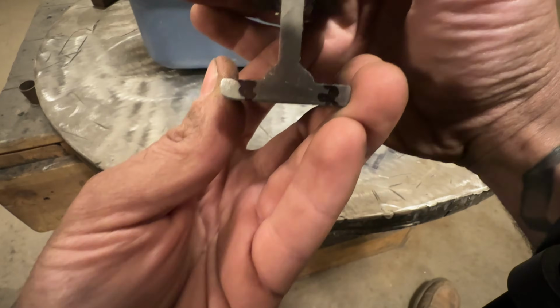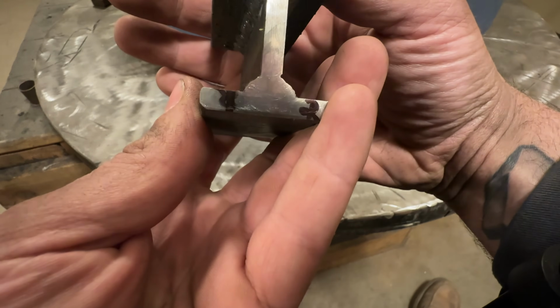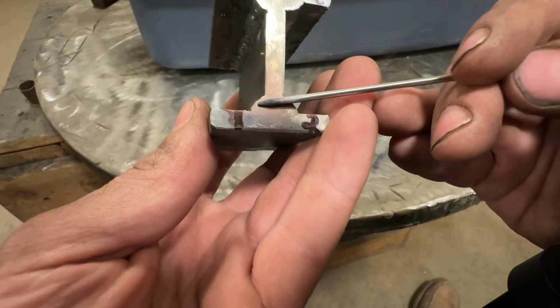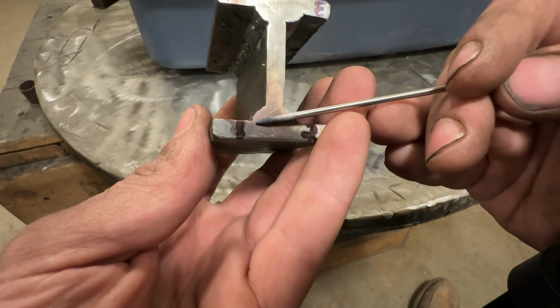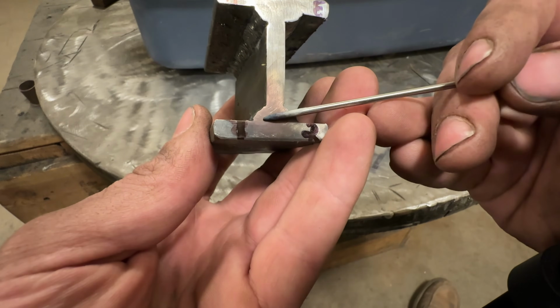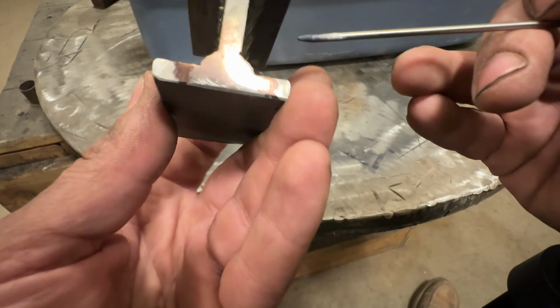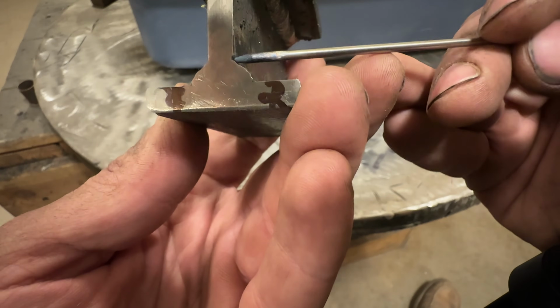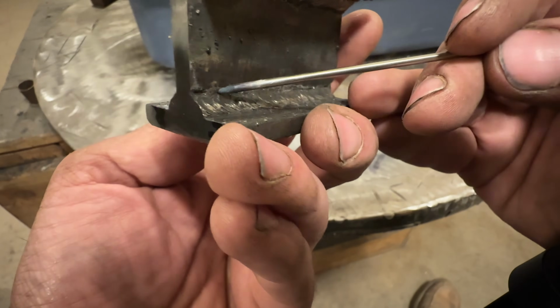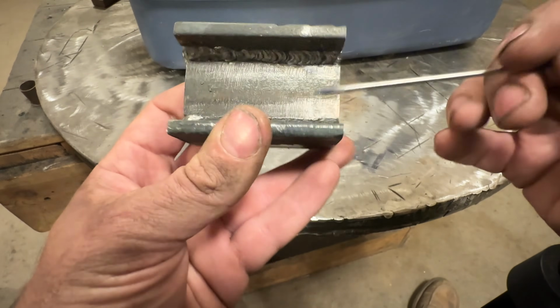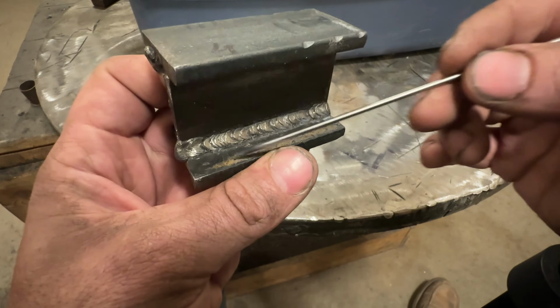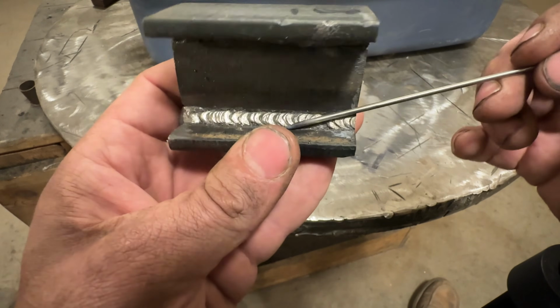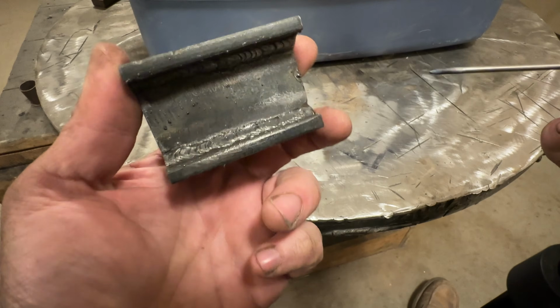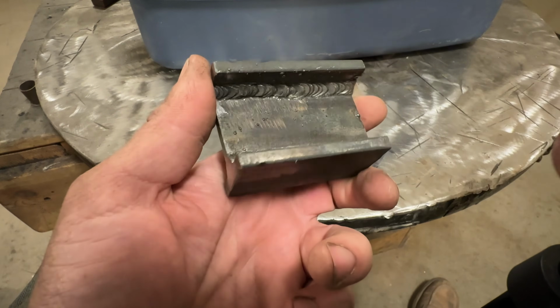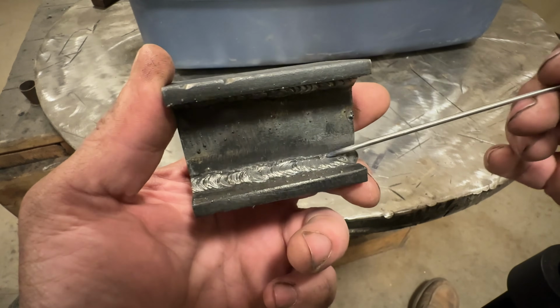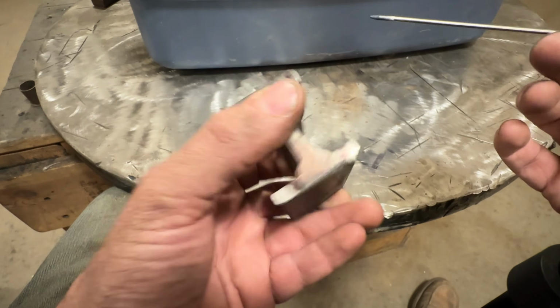And if you look at that, I'll bring it up to you. We're looking for slightly convex. We don't want to see concave where it's very thin in what's called the throat of the weld. We don't want to see too much undercut, like we got undercut right here. Very clear evidence. But as far as acceptability, these stick welds don't look too bad. Clearly it's a 6010 or 6011 rod, something in that. Not too bad. We don't see excessive spatter. We don't see tons of slag inclusions.